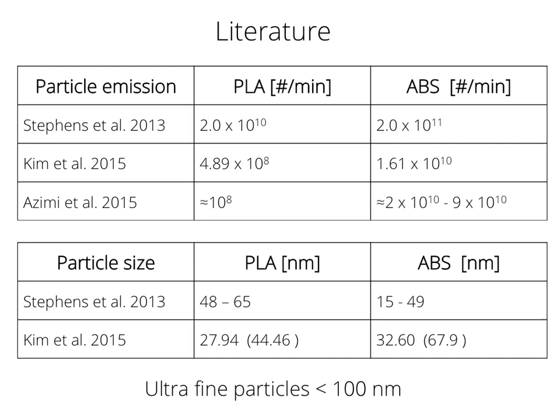Particle size was also investigated by Stephens et al. in 2013. They measured that PLA emits in a particle size range between 48 and 65 nanometers, or at least that's where most of the particles are emitted, in that particle size range, and ABS emits in a particle size range between 15 and 49.